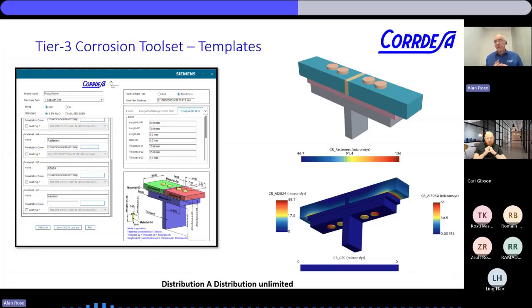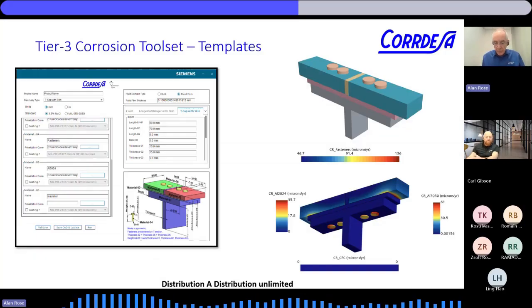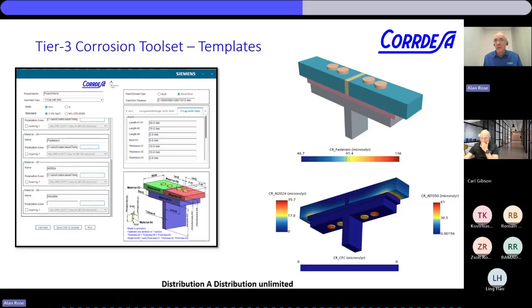And then it's really good that now they've decided that polarization curves are needed to get a more accurate handle on the corrosion rate. You cross the curve and you're just using a fraction of that curve where that intersection point is when you look at that table of pre-calculated corrosion rates. But if you use their polarization curves as boundary conditions in a 3D model, you can simulate and solve for potential and current density. It's kind of like temperature and heat flow. You can actually solve for that and you can get the corrosion rate on all your different materials.